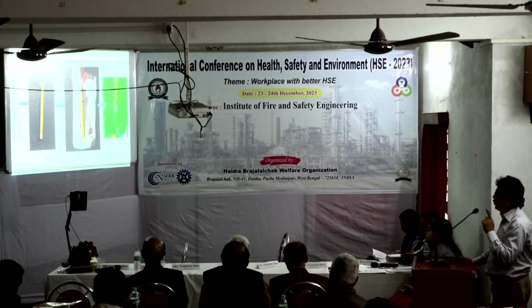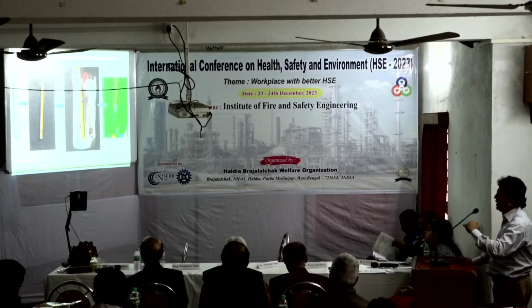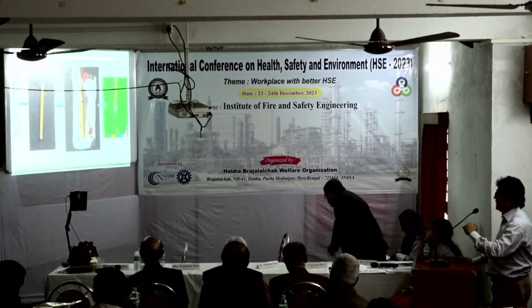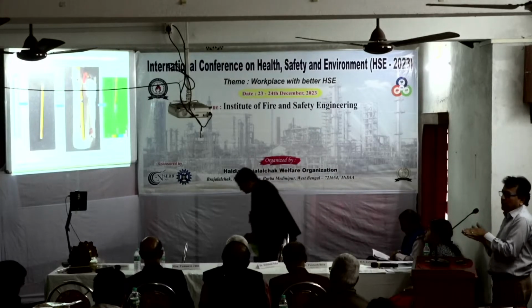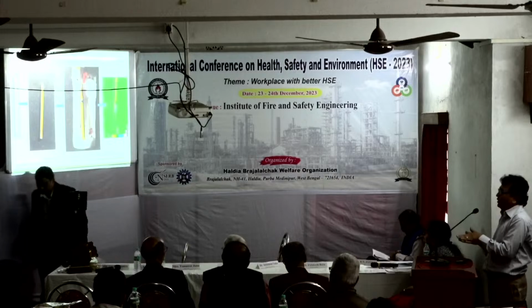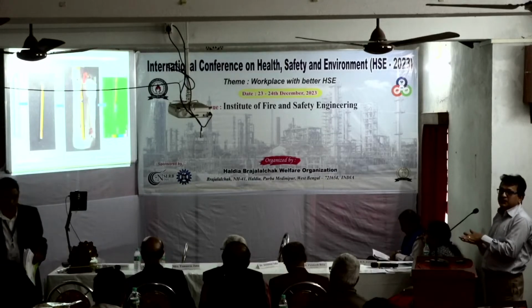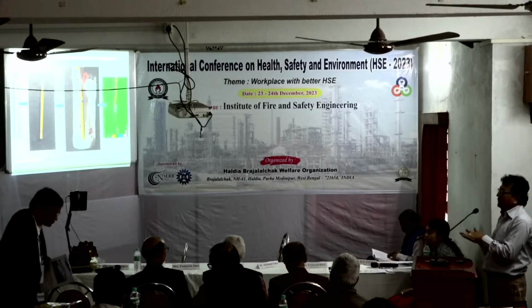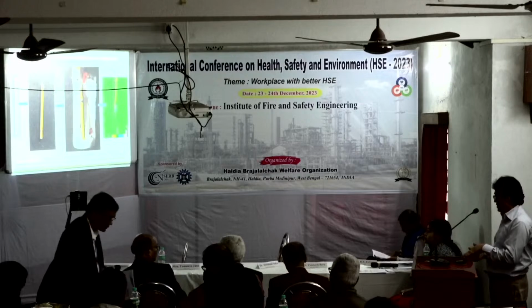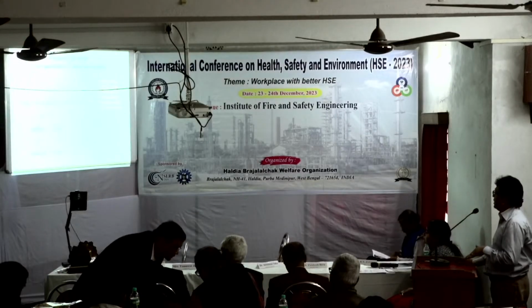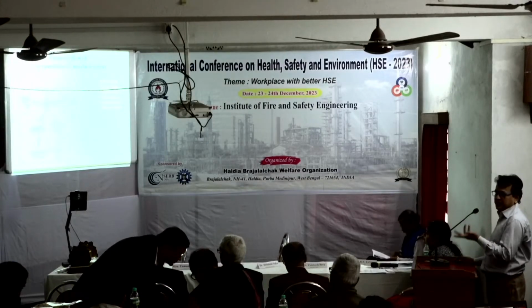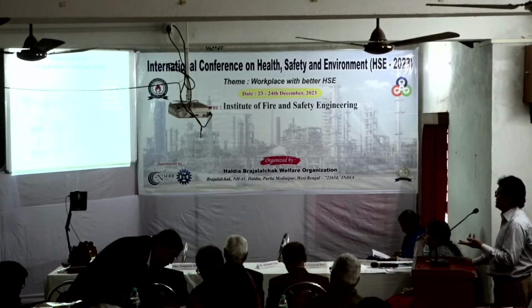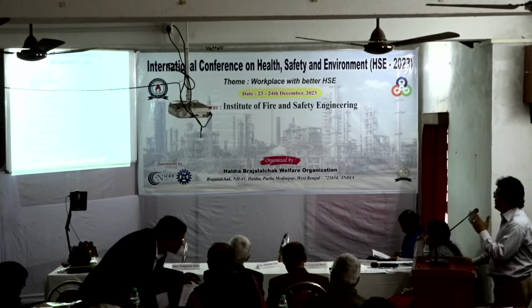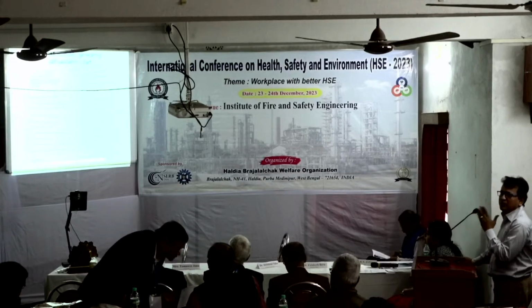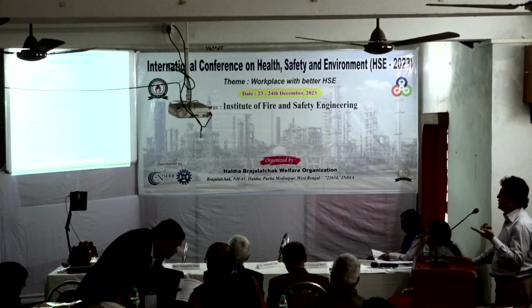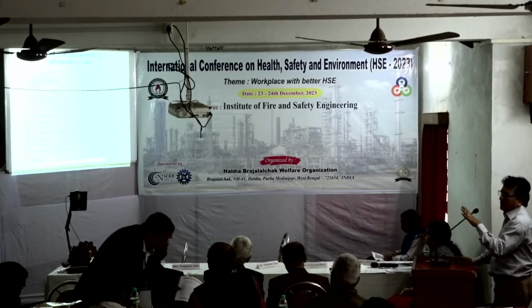So we used gold, then gamma alumina as the sensing layer, then the top electrode. There are two electrodes, the bottom electrode and the gold top electrode, and inside is the porous structure of the gamma alumina. The gamma alumina is the sensing layer, a nanoporous structure. The Sol-gel process was already explained by my colleague previously. This is the relative humidity generation using solid solution. The universal method generates the relative humidity, and no standard solution is required.